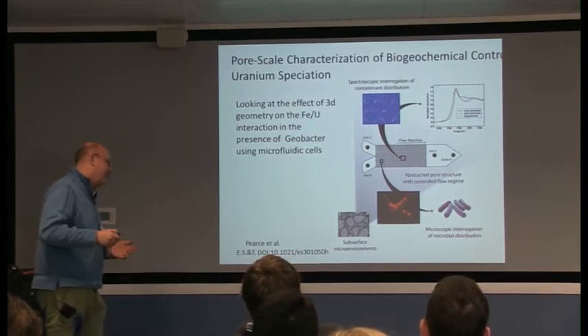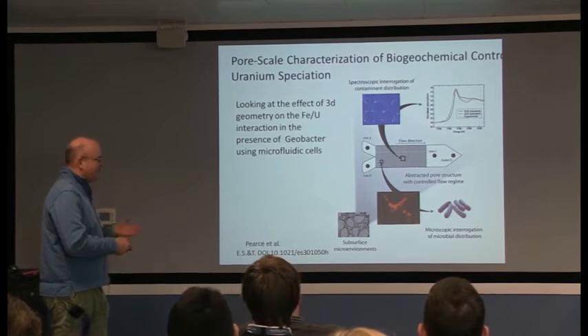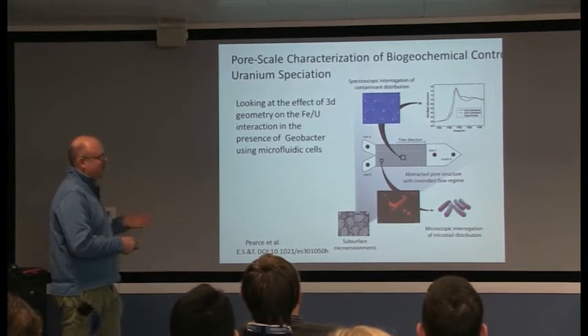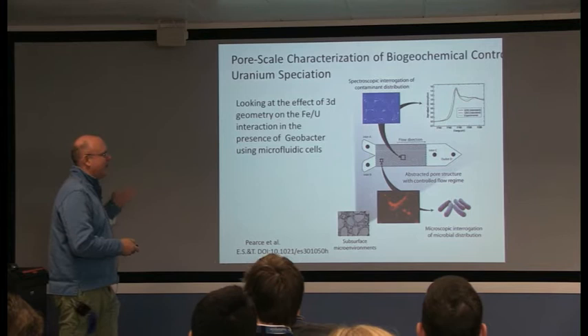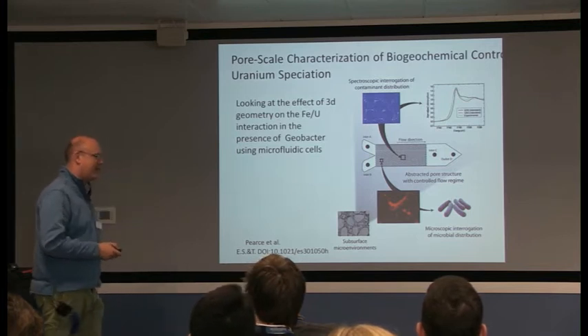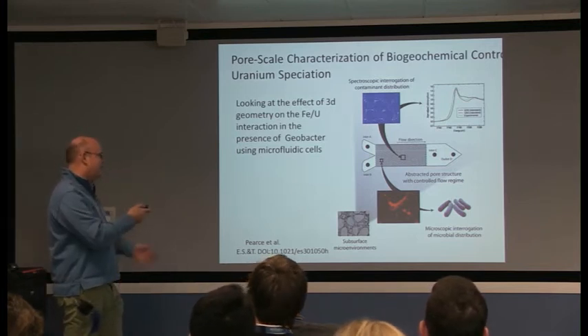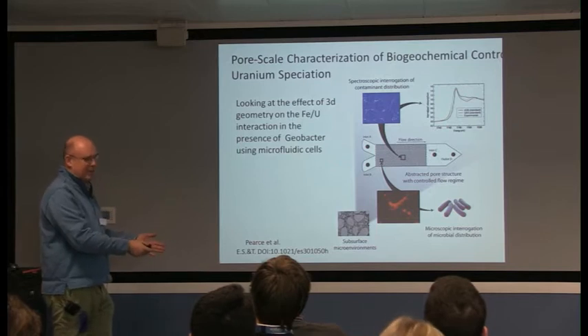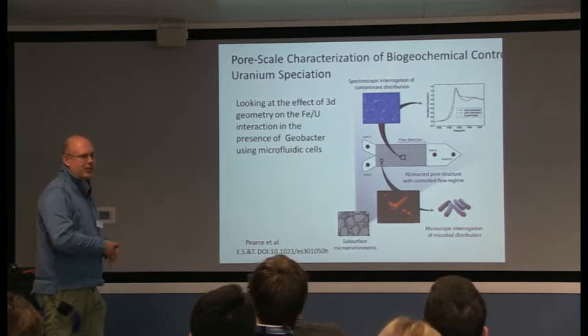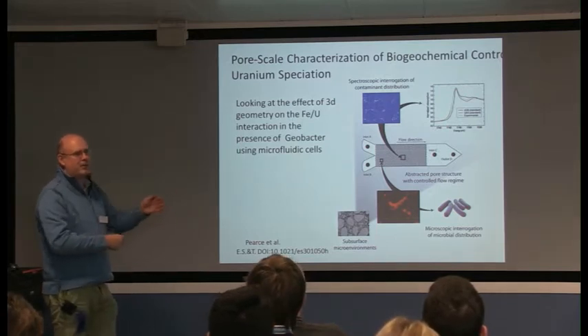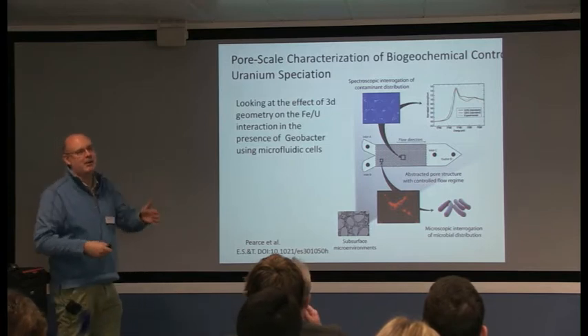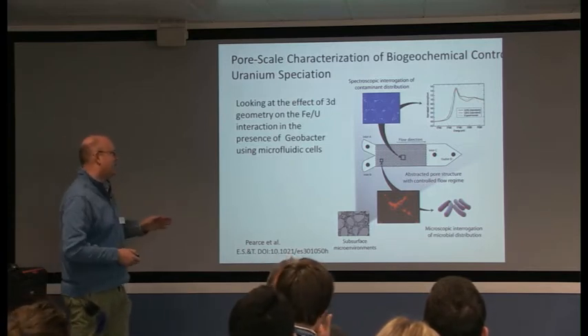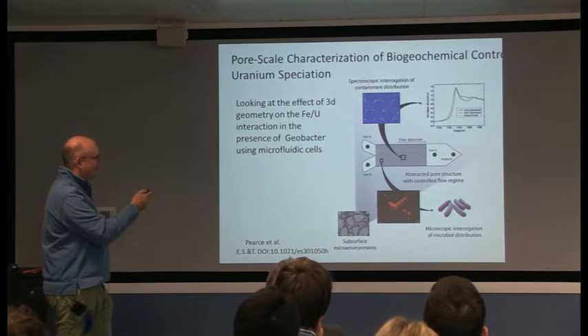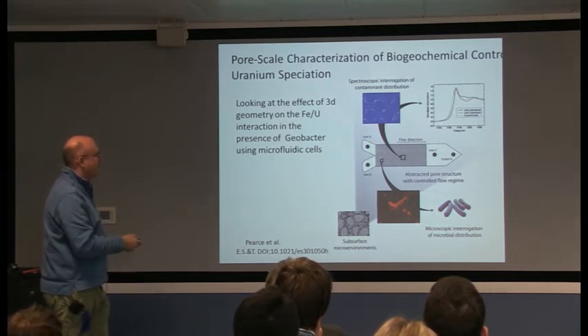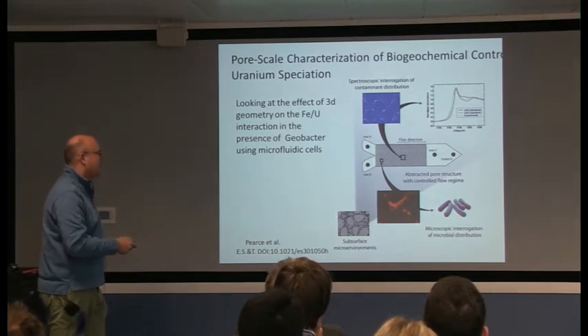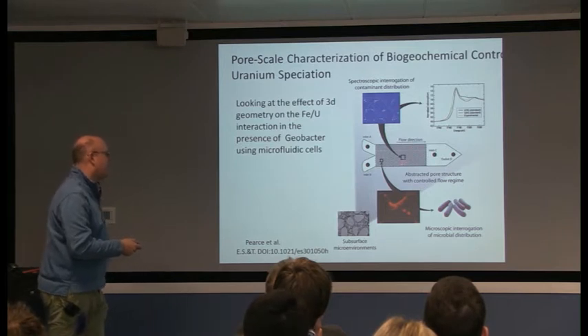How does that affect the interaction between iron, uranium in solution, and bacteria in particular? If you do a batch experiment, everything is perfectly in contact with each other. But if you've got flow and the bacteria hidden behind the pillars, and the flow doesn't go where the bacteria are, you may not get the same reactions. So she's built these microfluidic devices, flowed iron and uranium through them, and built up a bacterial cord.